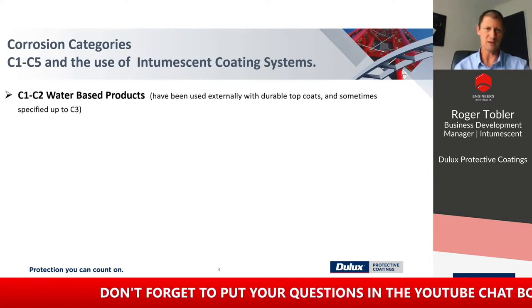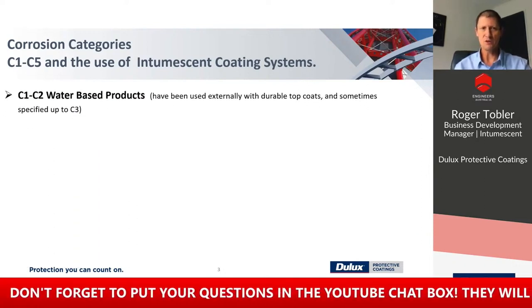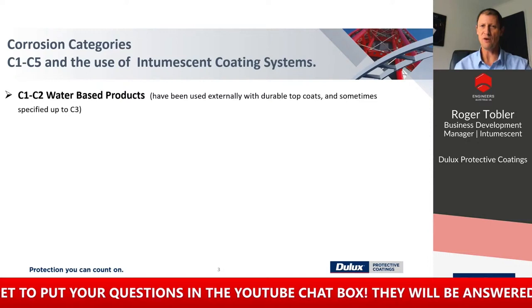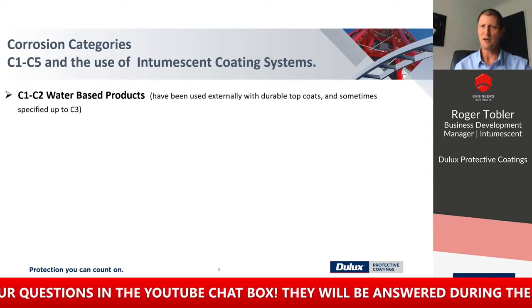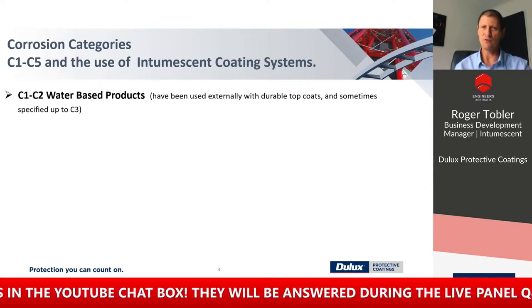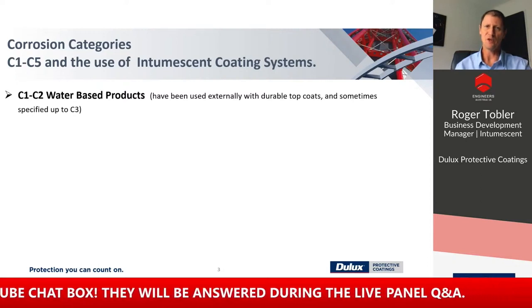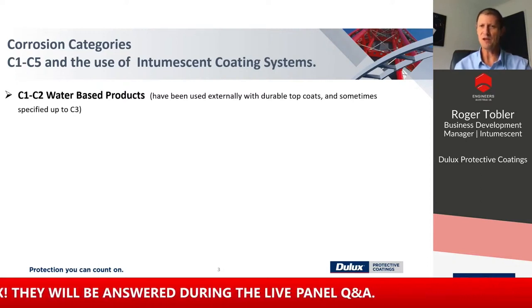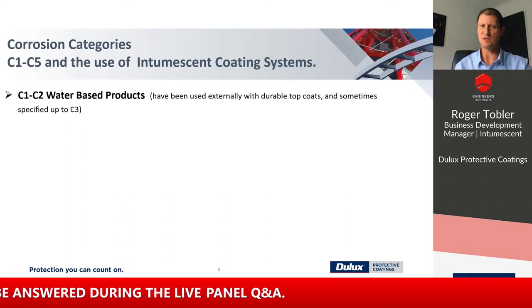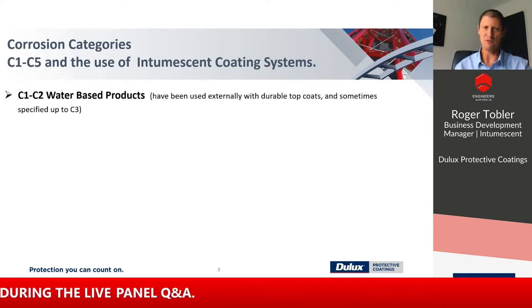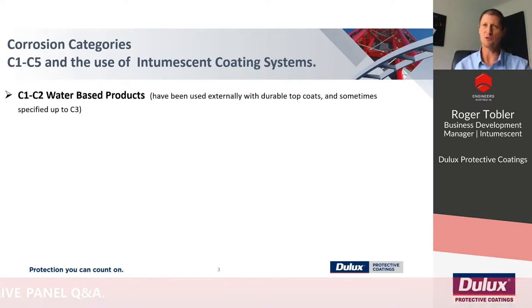First up, we'll look at water-based. Mostly used in C1 to C2 corrosion environments. These are really dry, not a lot of UV. There's no moisture in these environments. Sometimes intumescent coating companies will specify them up to a C3 environment, but largely not exposed to moisture.